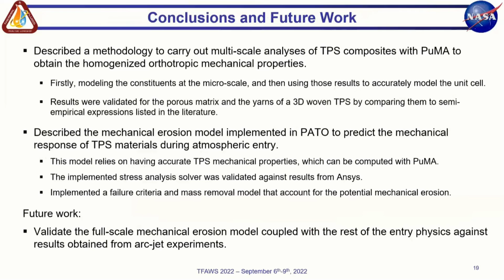So to conclude, we described a methodology to carry out multi-scale analysis of TPS composites with PuMA to obtain the homogenized orthotropic mechanical properties. Firstly, we model the constituents at the microscale, and then we use the results to model the unit cell. And the results were validated for the porous matrix and the yarns of a 3D woven TPS composite by comparing them to some empirical equations listed in the literature. In the second part, we described the mechanical erosion model implemented in PATO to predict the mechanical response of TPS materials during the atmospheric entry.